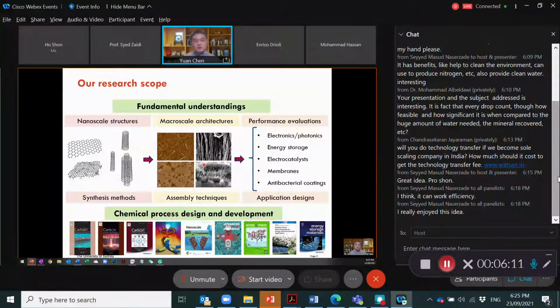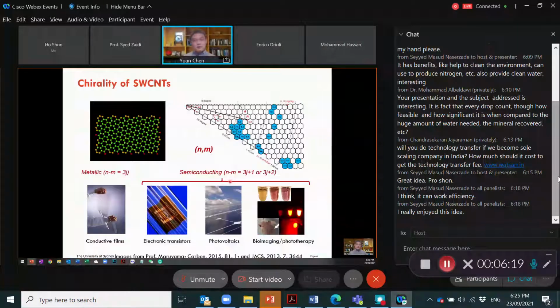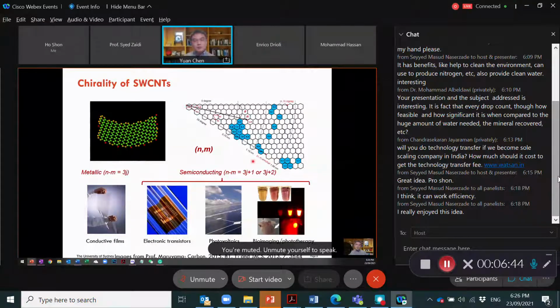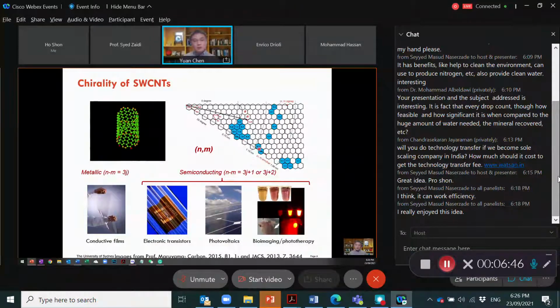So my research team basically are focusing on these two issues, and then we'll go into the different applications. So for the first area, which we have been working on for many years, is about the structure control of the single wall carbon nanotube. So nanotube you can consider as a hollow, one-dimensional graphene you roll into a pipe, and depending on which direction you roll this graphene layer, so this is the starting point, you can link this point to any other point on a graphene sheet, and then you will get the nanotube with a different diameter at the same time with a different rotation.